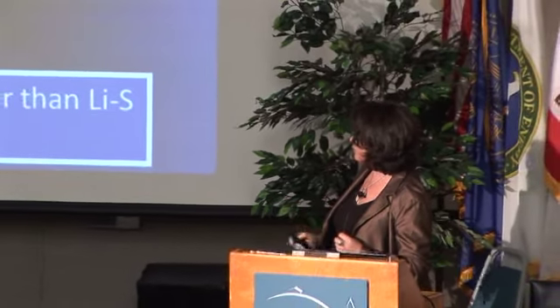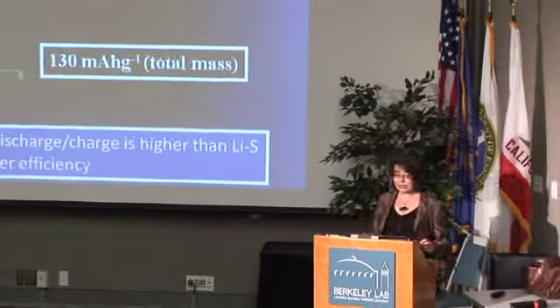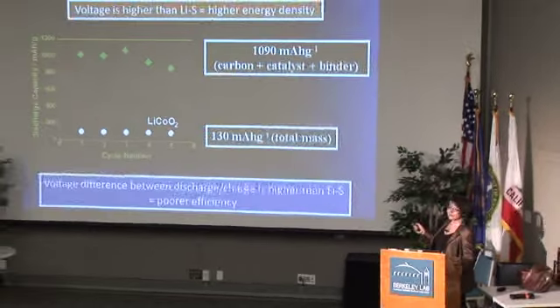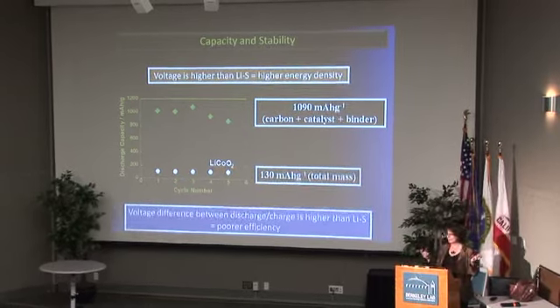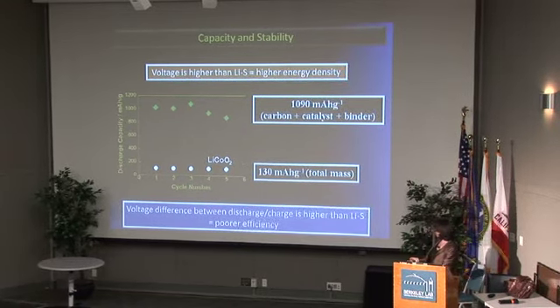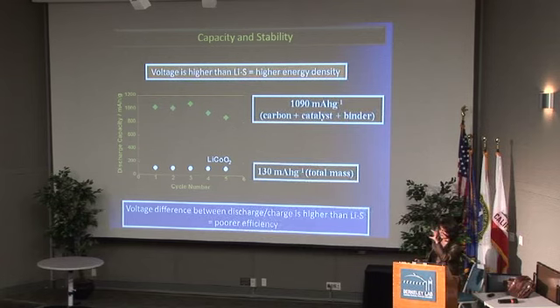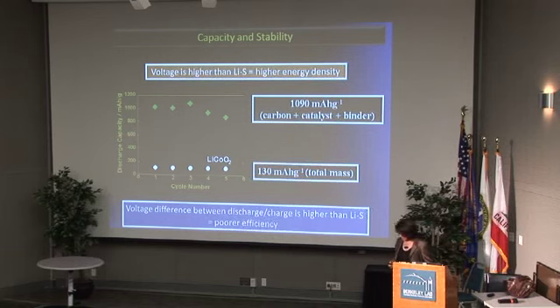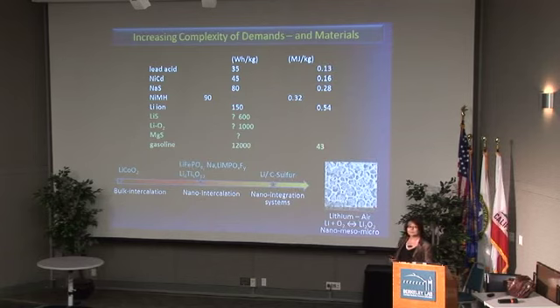So when we count up the binder and the catalyst and the carbon, we're looking at about 1090 milliamp hours per gram capacity over those few cycles compared to lithium cobalt oxide. So I'll just remind you that the voltage is higher than lithium-sulfur, so that gives rise to a higher energy density, so we can easily get 2,000 watt-hours per kilogram, but really with poor efficiency because it's still of that overpotential. So if anyone had to ask me where I put my money, it would definitely be lithium-sulfur, but the fact is that there's a lot of intriguing work to be done in lithium-oxygen, I think, as the understanding really expands.